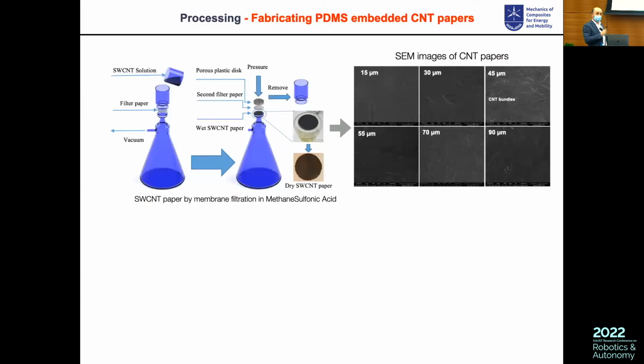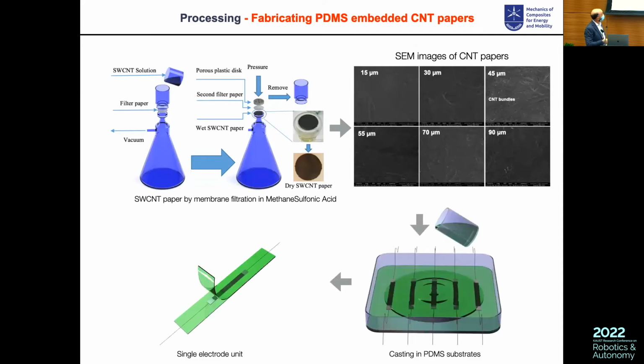So here again, what we engineer now is only the electrode part of the capacitive sensor that is going to come in your wireless system at the end. I will go quickly on this because it's not the point of the talk today, but you make CNT paper, with any technique. You make filtration of a bath with a suspension of nanotubes, for example. At the end, you get papers of CNT that are pretty much randomly aligned in plane. You filter this, and then you can get strips like this that are conductive strips of CNT, right? This strip is already piezoresistive, but it's through the normal network of nanoparticles.